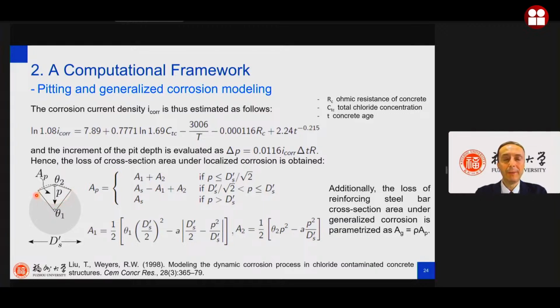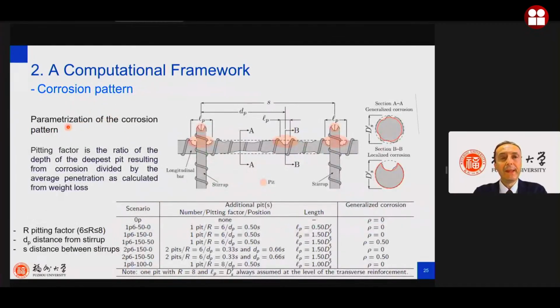There are different methods to approximate the geometry of the pitting, but we use this one because for us it's accurate enough, and in the meantime not so complex to be implemented. And after, we did a parametric analysis considering different possible corrosion paths. So we did not consider only the generalized corrosion, but also the localized corrosion, and we consider that the worst condition could be the formation of one pit in the middle between two stirrups, and after a high probability to have a pitting at the stirrup location.